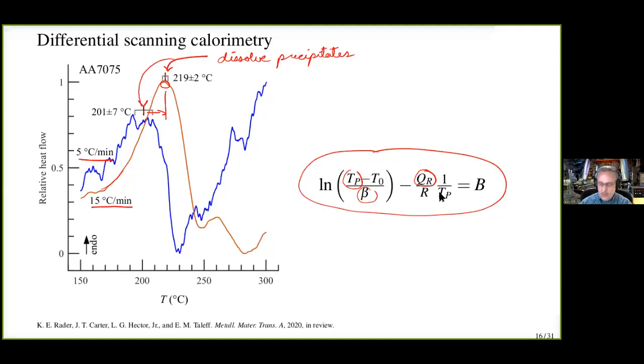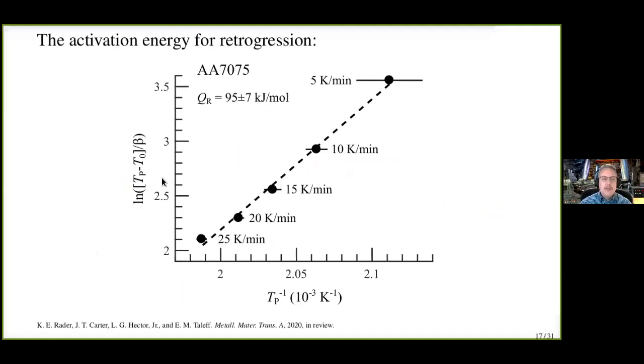So if we use this equation, we can then plot this part of the equation versus the inverse peak temperature. And the slope of this should be Q over R. And what we see is using 1, 2, 3, 4, 5 different heating rates, we get a very nice linear plot, which tells us, yeah, activation energy for retrogression is about 95 kilojoules per mole. And this is actually pretty much in line with the diffusivity of zinc in aluminum. So that makes a lot of sense.